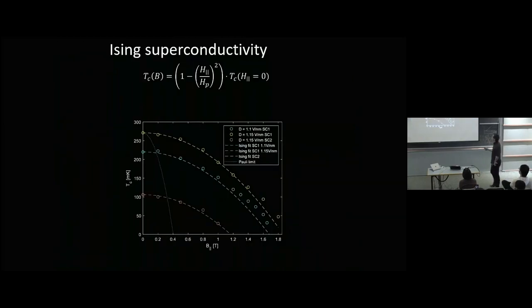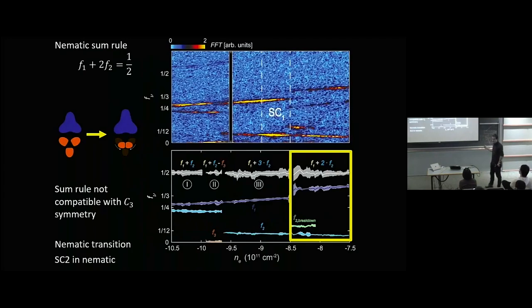And that's interesting because this nematic phase is exactly where the big robust superconductor is. It's just in the middle of this nematic phase. So you have this first-order-seeming nematic phase transition where one of the big Fermi surfaces eats one of these small pockets, and then inside that phase you have a superconductor that has 10 times the TC of what you had before.